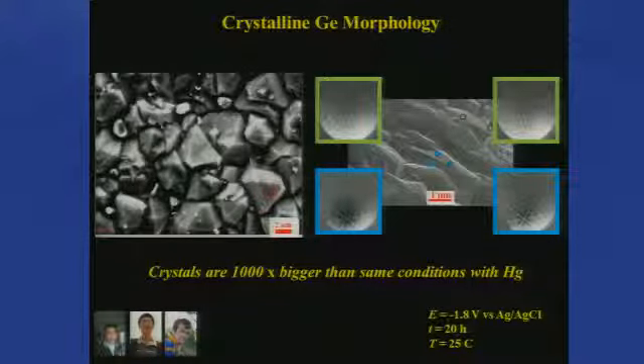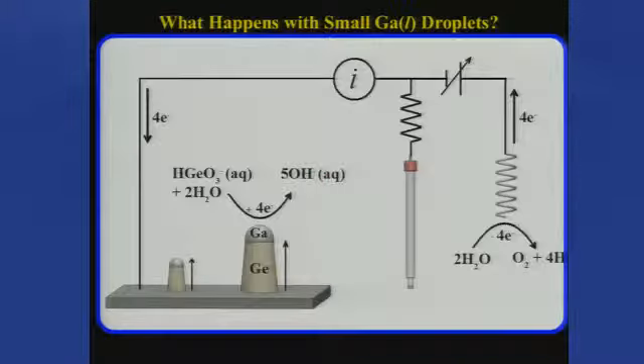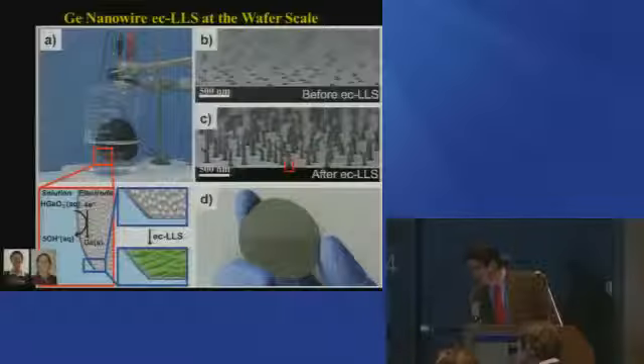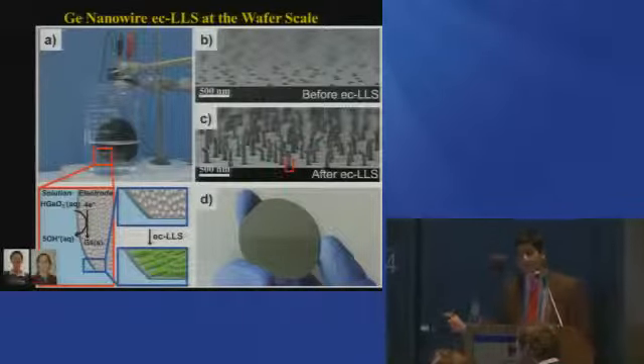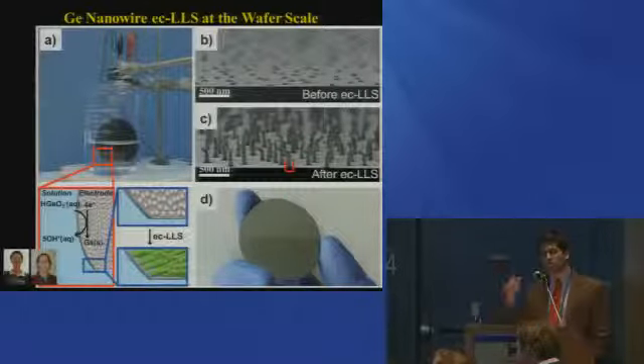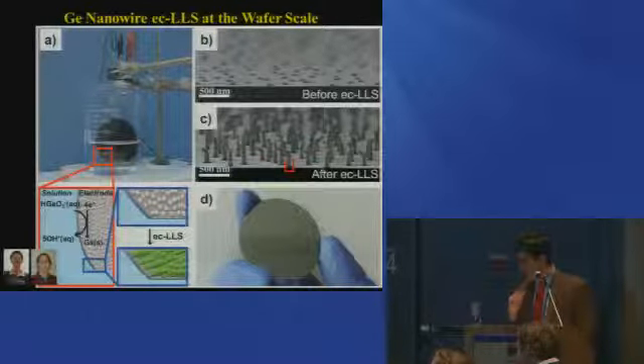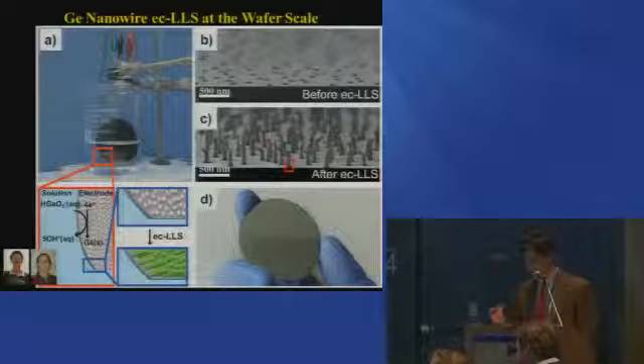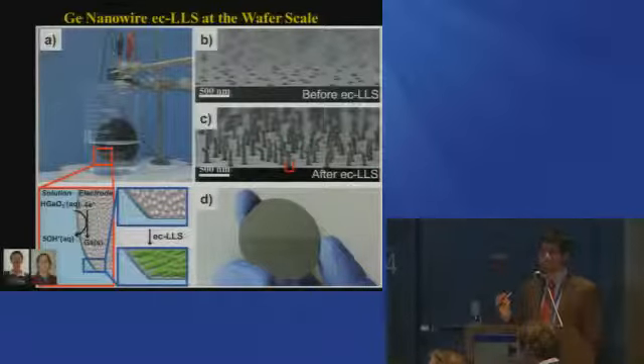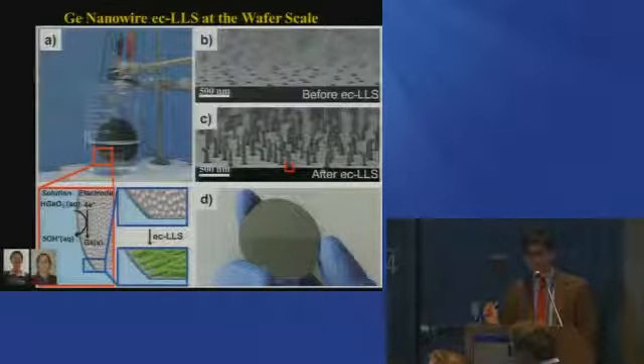You get a bigger crystal because gallium is a better solvent for growing germanium. Again, we've been thinking about doing this experiment, trying to grow high-quality single nanowires, and now we're going to try to use tiny little gallium nanodroplets. This is what that experiment looks like. I'm thinking we're getting into a phase where we're not, by any stretch of the imagination, complete or near the finish, but we're now starting to get to something that becomes interesting to think about.